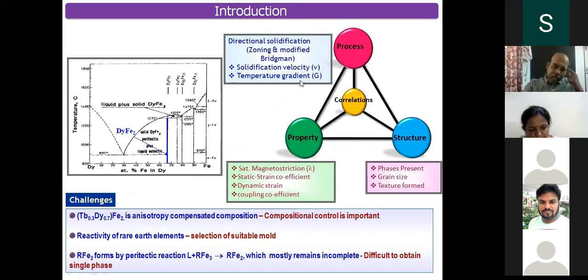The processing technique we adopted here is a directional solidification technique, and we have used two techniques. One is the zoning technique, the other is a modified Bridgman technique. Here we have two parameters which we can play around with. One is the solidification velocity. Here, we melt the material at high temperature using a seed crystal, and we slowly pull it from the high temperature zone. The temperature gradient is the difference in temperature between the seed and the melted portion. The greater the temperature gradient, the more orientation we can play around with.